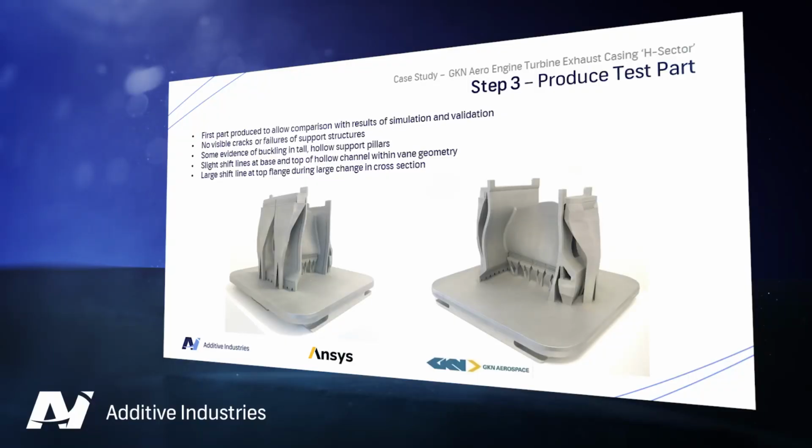The first part we produced based on this support design allows comparison with the results of the simulation carried out by Ansys. What we found with the first build, as you can see on the pictures, is no visible cracks or failure of support structures. However, what we do see is some buckling of the tall hollow support pillars, and we also see some shift lines at the base and top of the hollow channel within the vane geometry of the component. Also, a very large shift line appears on the top where we have a large change in cross-sectional area at the top flange of the component. These are all areas that we need to focus on with the subsequent compensation.